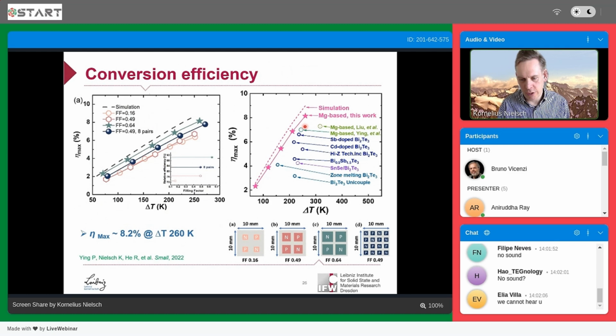And if you compare, for example, the performance of our device with a number of reference data, you can see that we are very competitive with telluride modules, but also with other references of magnesium-antimony based modules. So we have a very steep increase, just applying 250 Kelvin and having already 8%. And there's definitely more room for improvements, going beyond 10% by using this device.